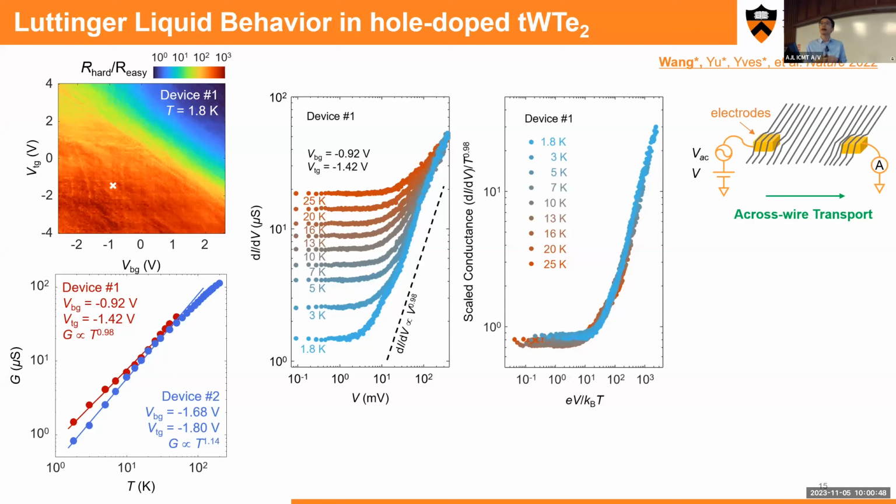And I think it indicates some number of how many wire tunneling processes you might have in this system. If you simply suggest it is a single wire system and it keeps tunneling from wire to wire, then you might anticipate some number of tunneling processes equivalent to each other that keep tunneling to the next contact. So in this situation, it suggests you have around 30 equivalent tunneling processes.